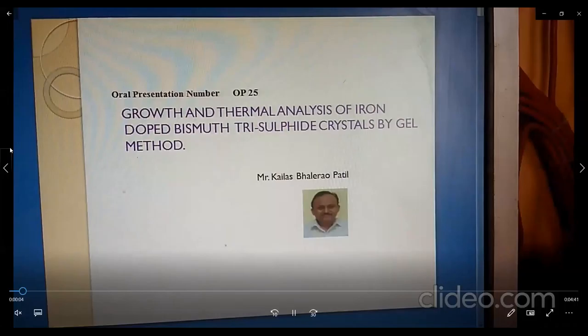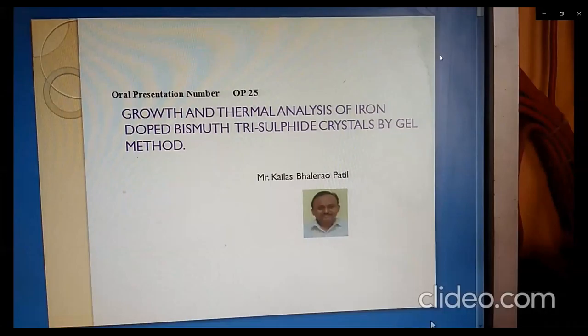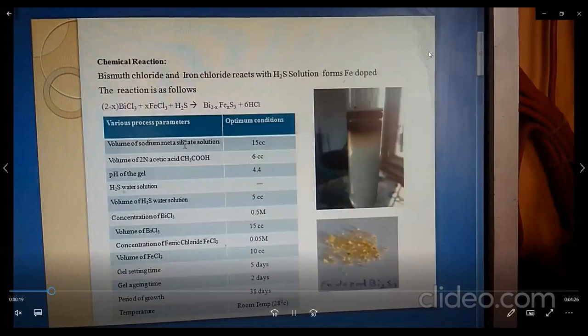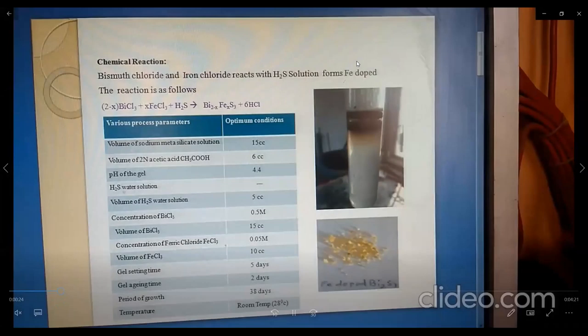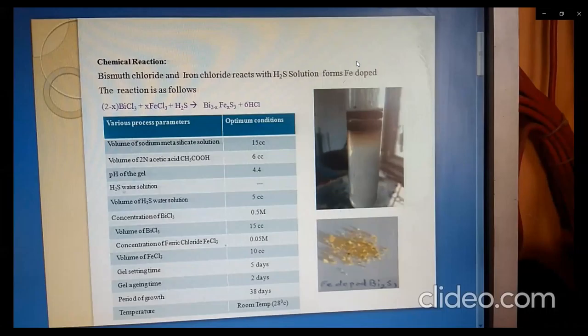OP25. Title of my presentation is Growth and Thermal Analysis of Iron Doped Bismuth Trisulfide Crystals by Gel Method. This is the chemical reaction for iron doped bismuth trisulfide crystal: (2 minus x) BiCl3 plus x FeCl3 plus H2S gives Bi(2 minus x) FexS3 plus 6HCl. The table shows the optimum conditions